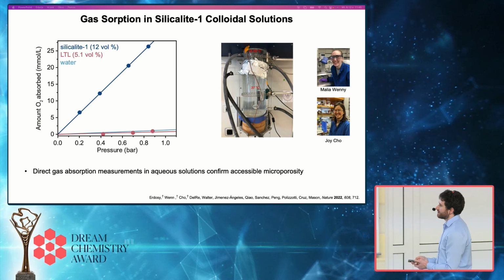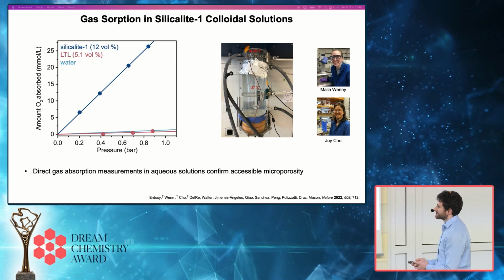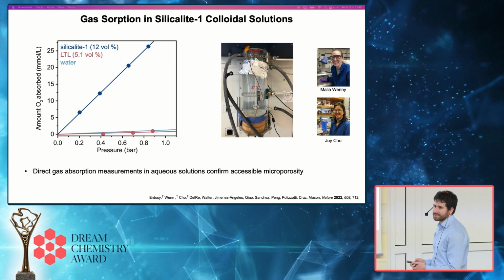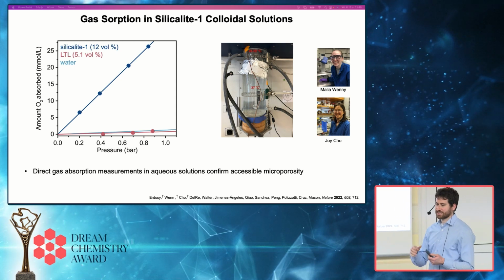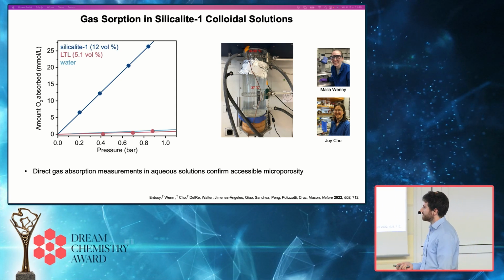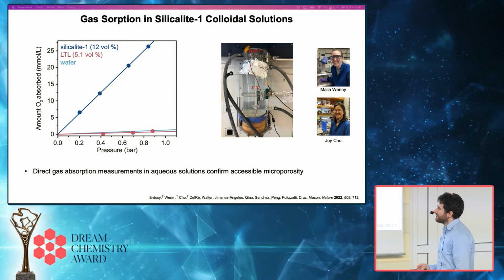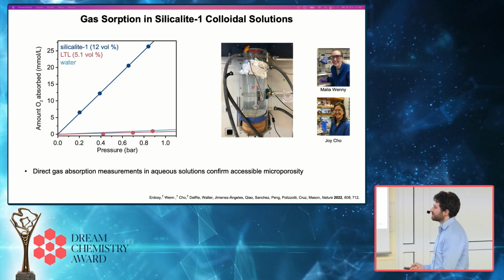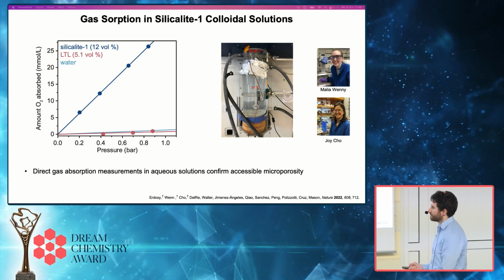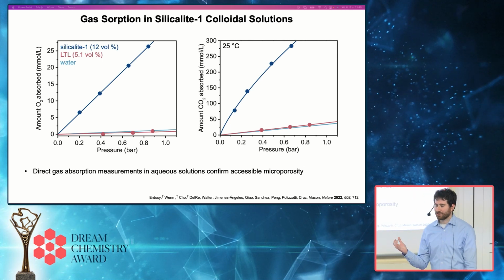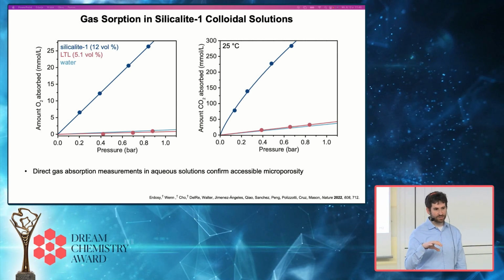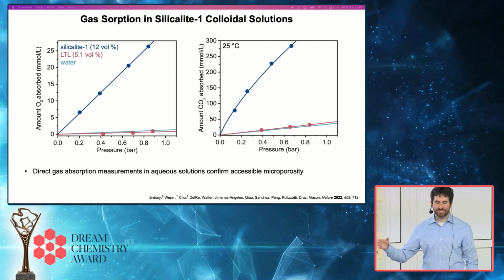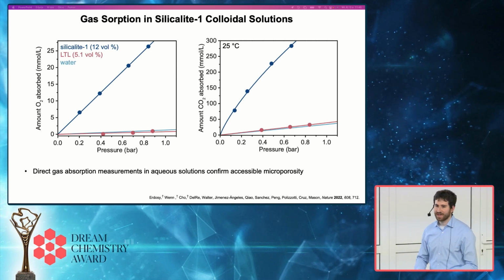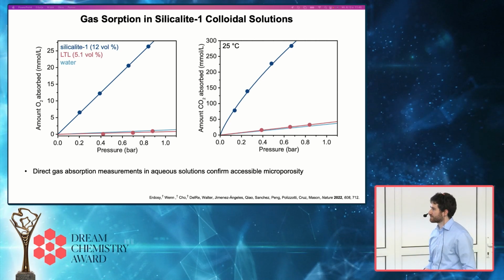And so what we see is in our hydrophobic zeolite dispersions, significant enhancements in the amount of gas that's taken up by these aqueous solutions, both for oxygen and carbon dioxide, compared to a dispersion of a hydrophilic zeolite and compared to water. And so this is directly confirming that the pores of our materials are not only dry, but they're accessible to gas molecules and still able to absorb gas molecules even in this kind of dispersion.